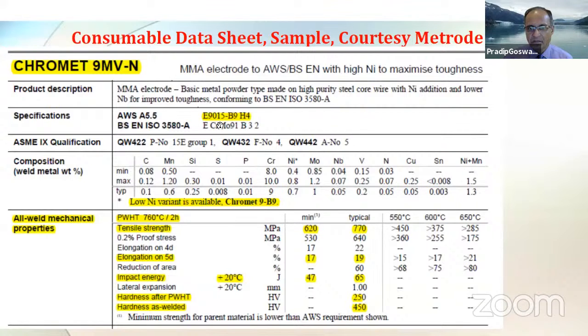As you see here, typically they are H4 category, and these are typical chemical composition. And you see here the typical nickel plus manganese is 1.3%. One can expect this with this brand. And these are typical mechanical properties.